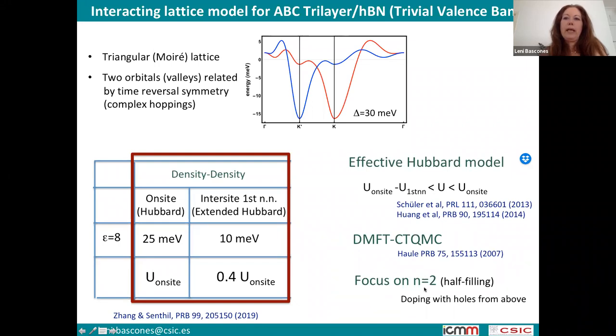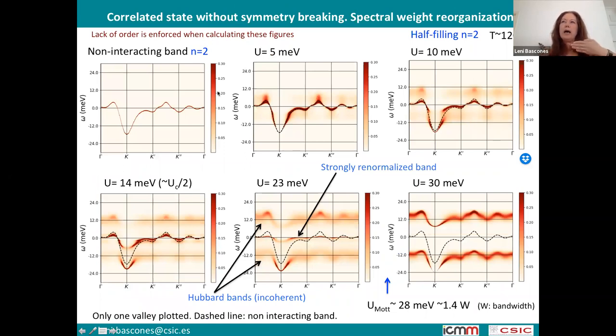I'm going to focus on half filling, in the particular case in which we have two holes doping from above. First, I'm enforcing no symmetry breaking. And here you can see that, as we expect also happens in other Mott systems, there is some spectral weight reorganization. This is the non-interacting band, and we are increasing U. One can see how this band is pushed to higher energies, and these bands are renormalized, becoming thinner, and at some value of U, which is of the order of 28 millielectron volts, the system becomes insulating. And all the spectral weight is incoherent, so it's in the so-called Hubbard bands.